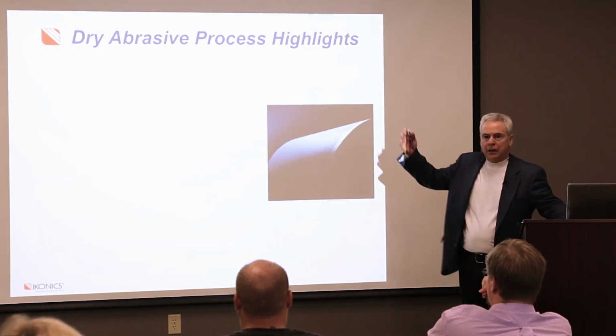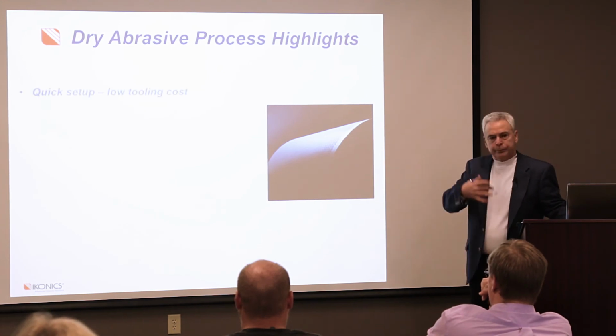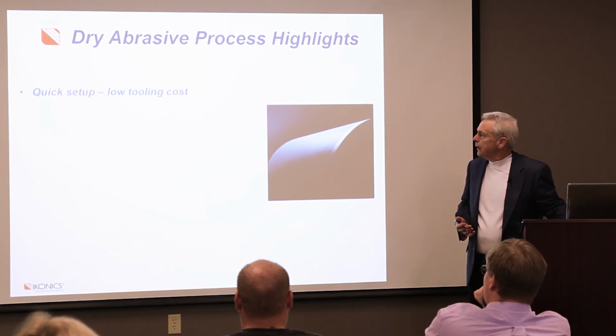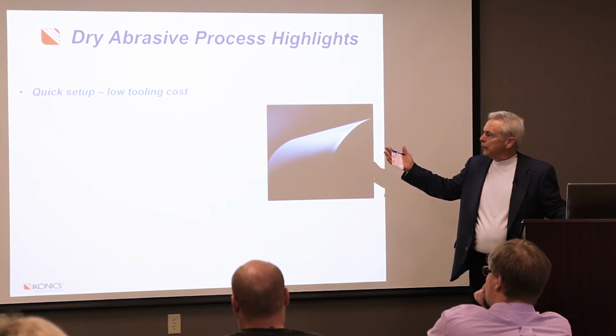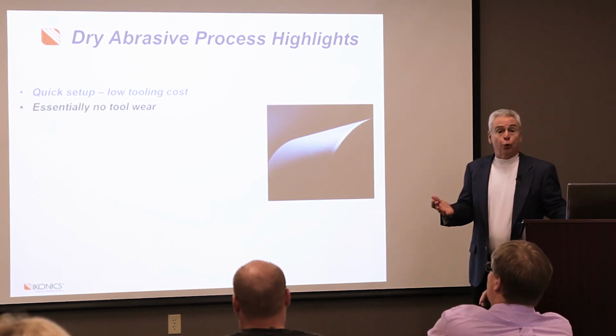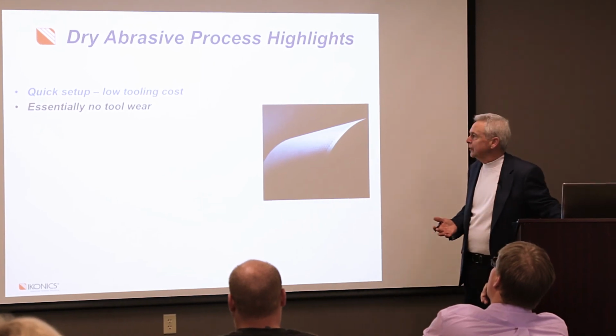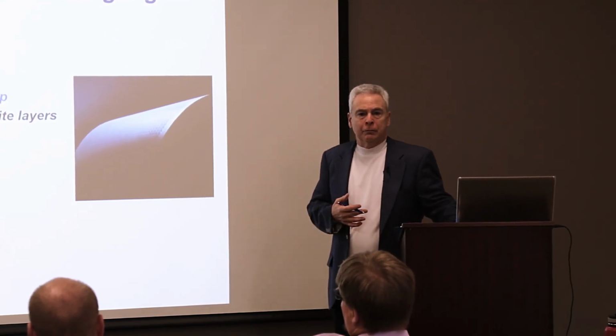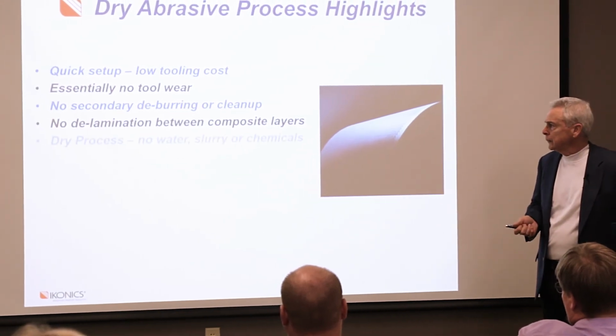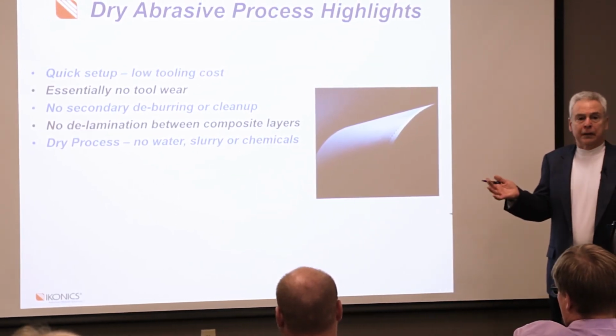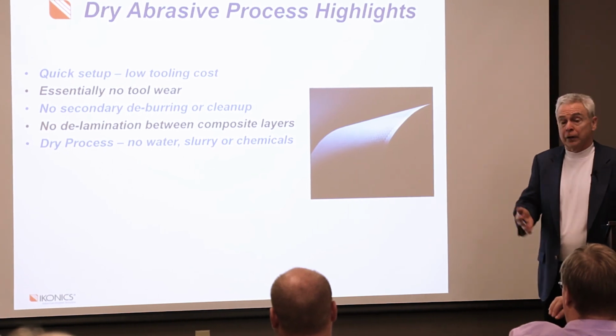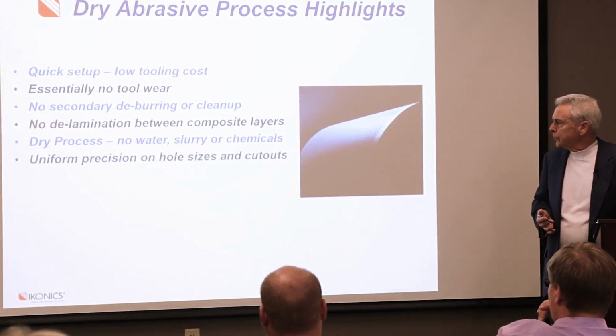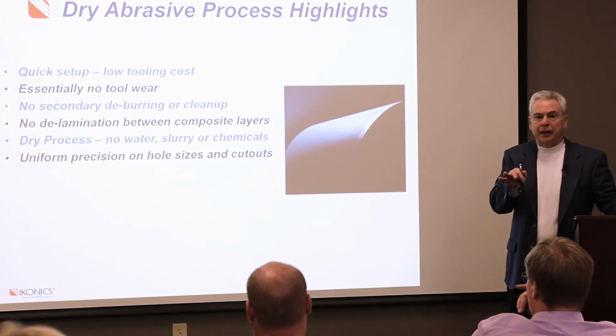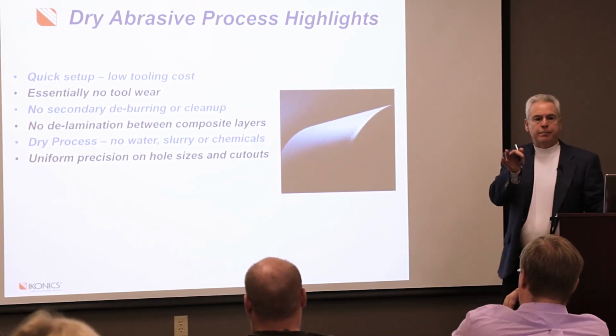So with that, in a summary way, just to take you back through what we've talked about today. We have a quick setup, very low tooling cost, essentially no tool wear. There are no tools to wear out in this process. No secondary deburring or cleanup is required. No delamination occurs at all between composite layers, and that's a big item for the aerospace industry. It's a dry process. There aren't any slurries or water used as you would for, let's say, water jet technology. Uniform precision on all the holes and the cutouts, because they're all the same. They're defined by the photoresist.